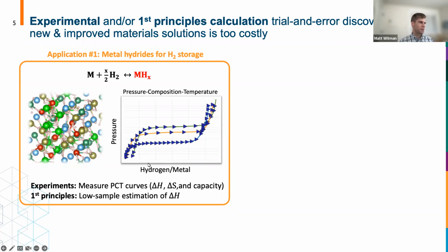But it takes a really long time to make and test these materials. And from a first principle standpoint, it's really, really hard, if not impossible, to do this exact PCT curve prediction from first principles, especially when you even consider looking at more than a few materials or doing this in high throughput. So the best we can kind of do is a low sample estimation of delta H.